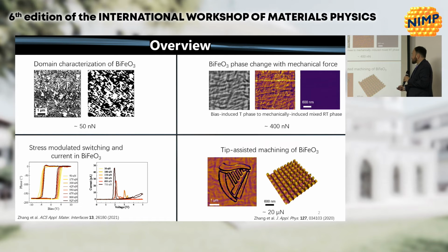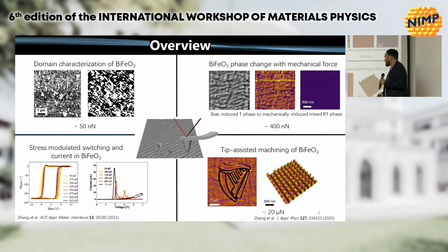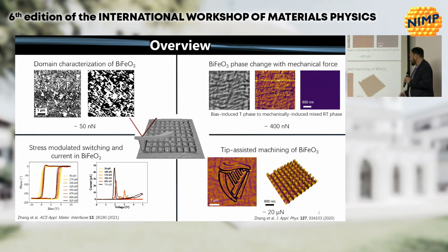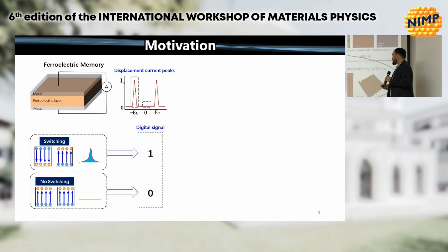And then in addition, what happens if we start applying a larger force? So that's going from just purely imaging or maybe cleaning the surface a little bit, to introducing a structural phase change, to enhancing switching currents and changing the coercive field, to actually modifying the surface with larger forces. So if we go to on the order of 20 micronewtons, we can do something like this and have the tip follow a loaded lithography pattern, or just an array like this. We can actually scratch the material and create nanostructures. So this is what I'd like to talk about today.